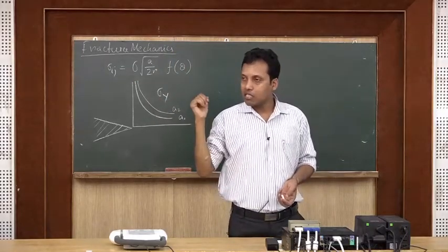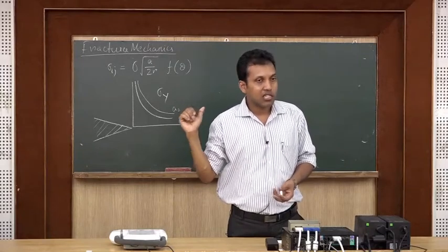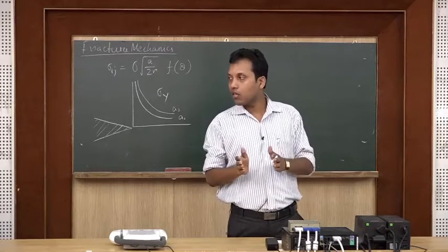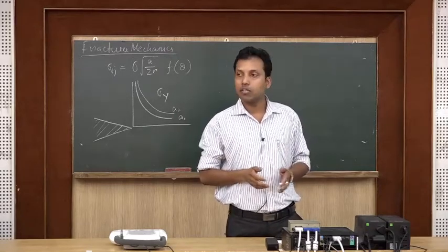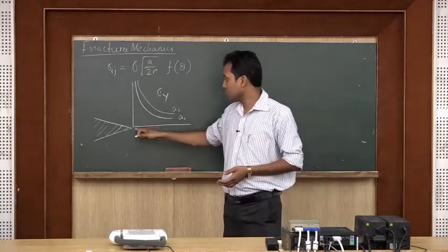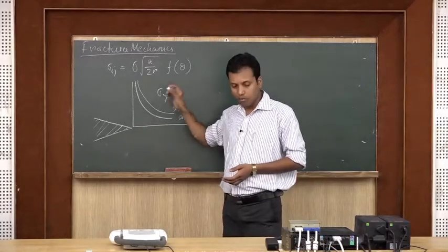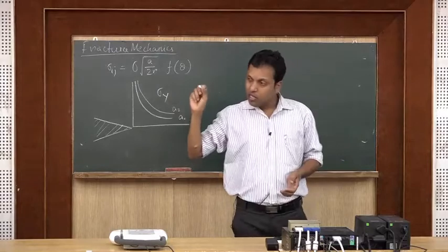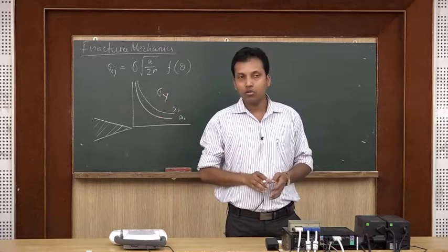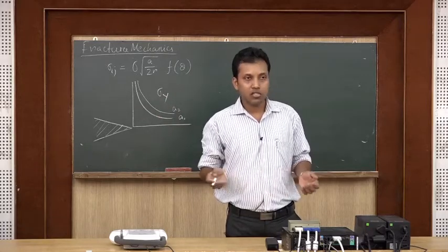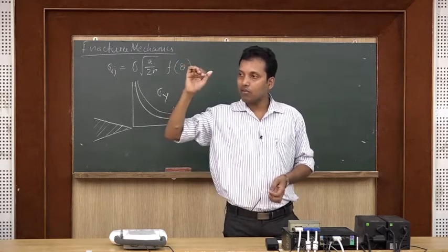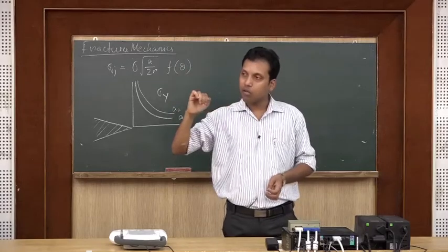okay. So this is although the elastic stress distribution, but we may have some region where plastic deformation is possible. Earlier we have seen that ahead of a crack tip we have considered some small tensile specimens, all of them will be trying to deform plastically, isn't it? Those things we have said. Why is this? Because of stress concentration. Stress concentration is there, so there will be increase in the stress level at the crack tip or some distance away from the crack tip.